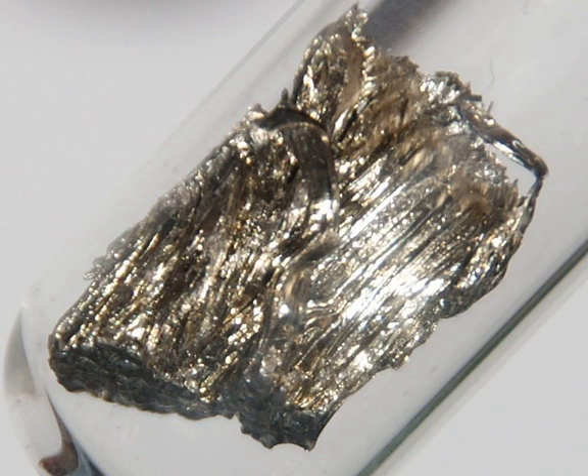The cooling-induced metal-insulator transition in SmB6 is accompanied by a sharp increase in the thermal conductivity, peaking at about 15 K. The reason for this increase is that electrons themselves do not contribute to the thermal conductivity at low temperatures, which is dominated by phonons, but the decrease in electron concentration reduced the rate of electron-phonon scattering. New research seems to show that it may be a topological insulator. Other inorganic compounds.